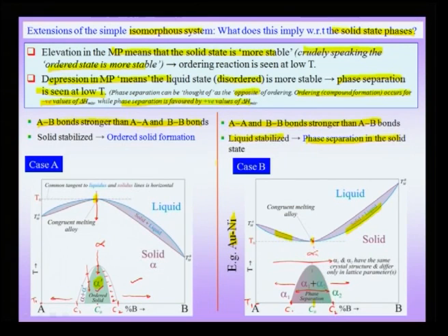Like for instance, alloys containing copper, which has a positive enthalpy of mixing with many elements, would tend to segregate at low temperatures and would form a suppressed phase. And suppose you took, for instance, the aluminum nickel system, then this would tend to rather form a compound than phase segregating at low temperatures.